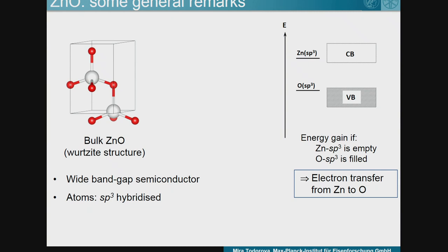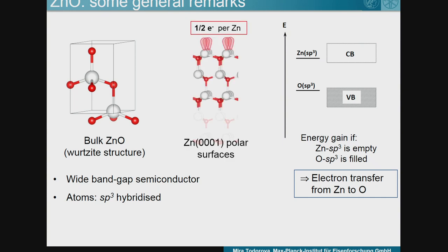Which means that in the bulk, each zinc atom would contribute half an electron to a bond, and each oxygen atom would contribute 3 half electrons to the bond. So each bond within the bulk has 2 electrons, which is the maximum number of electrons you can have in order to have a stable situation. Now, when we cleave the material perpendicular to the C direction, we end up with surfaces on one side which are purely zinc terminated and on the other with oxygen terminated surfaces.